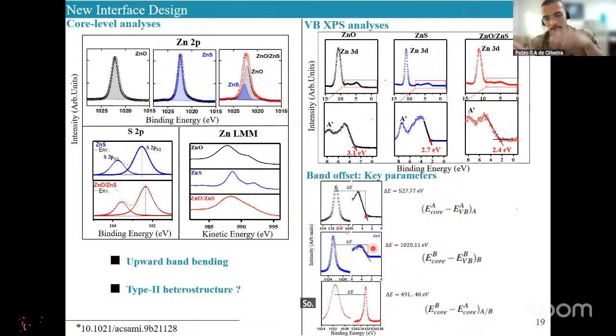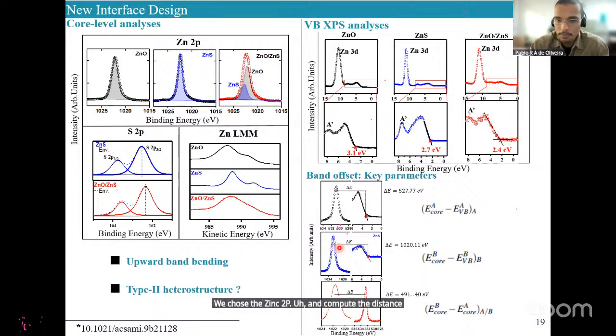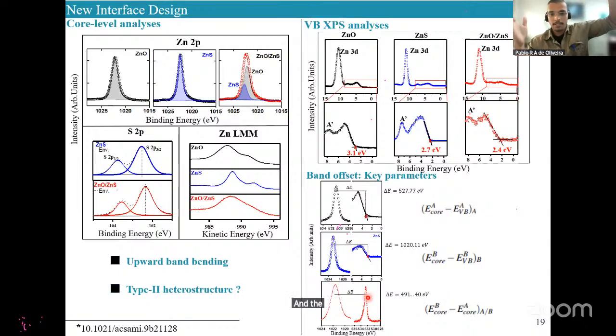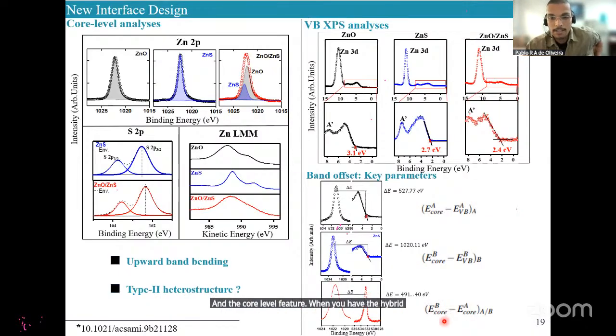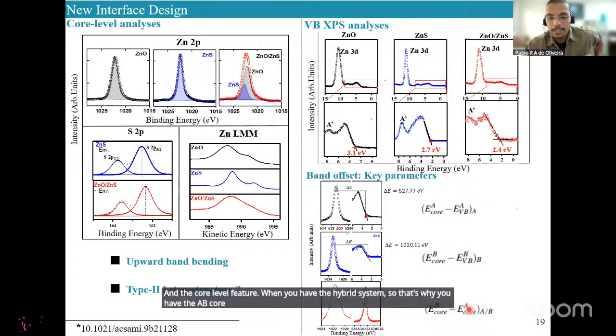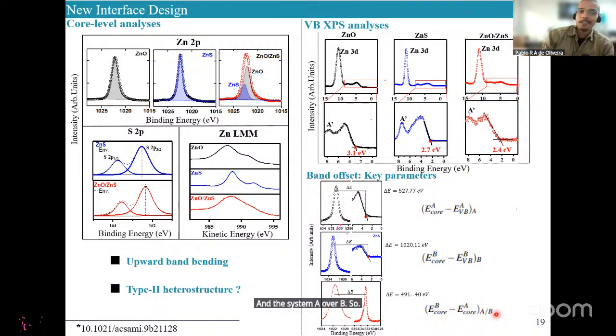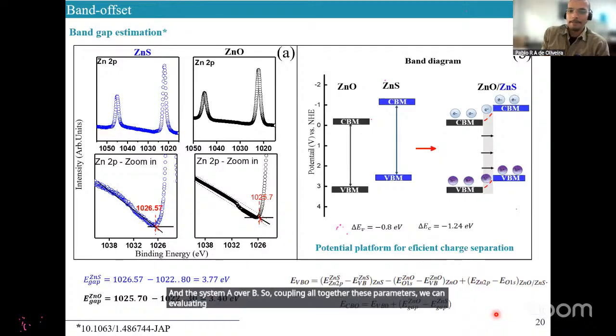Similarly for the substrate signal, we chose the zinc 2p and computed the distance between the zinc 2p peak and the valence band maximum when you have only the ZnS. And then finally, we compare the relative distance between the overlay feature and the core level feature when you have the hybrid system. So that's why you have the AB core, A core, and the system A over B. Coupling all these parameters together, we can evaluate the valence band and conduction band offset.